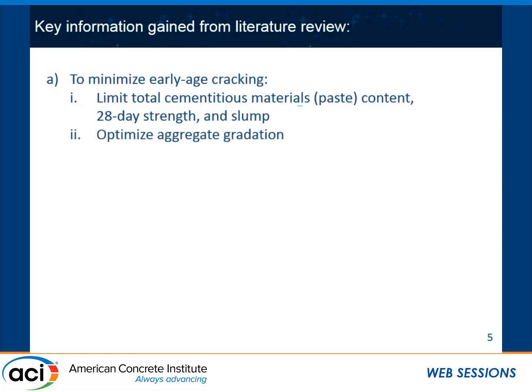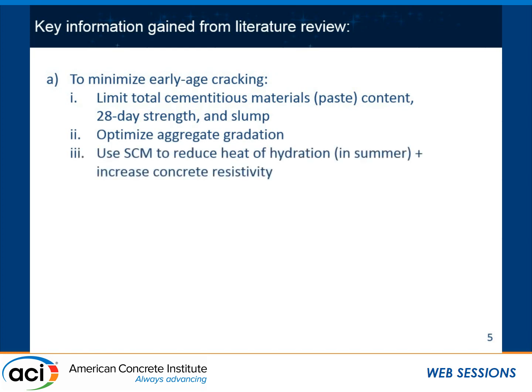Optimizing aggregate gradation would help with reducing the paste content and therefore reducing the cracking. Use of supplementary cementitious materials helps primarily through reducing the heat of hydration and thermal contraction, and also it has another advantage of increasing the resistivity of concrete. So once the concrete cracks and once you get the salts at the level of rebar, the resistivity of concrete would help slow down your rate of corrosion.